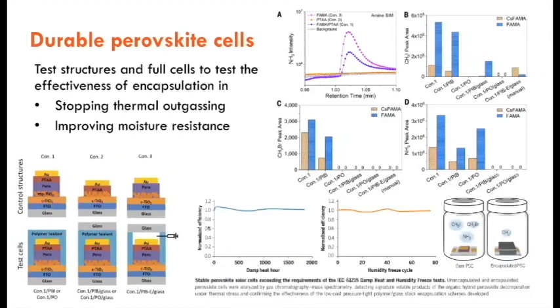So it does two things. The blanket encapsulation stops the thermal outgassing, but it also improves the moisture resistance by stopping moisture ingress. So using this scheme, we torture the cells again according to the IEC standard. So last time we managed to pass the thermal cycling. This time we subject them to damp heat and humidity freeze. So damp heat involves 85 degrees at 85% relative humidity for 1,000 hours. If you see only a 5% drop in efficiency, then you pass the test. But we managed to exceed the requirement by 700 hours.